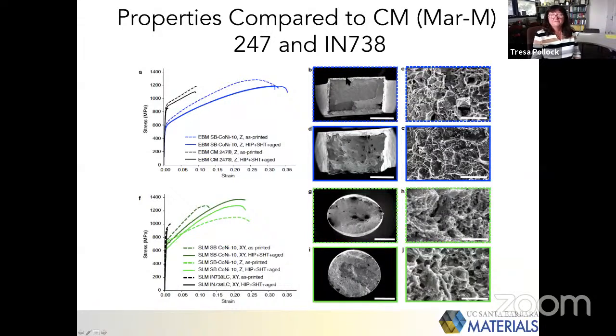And so recall the alloy I showed you earlier, Mar-M 247. This is the one that prints, that cracks very badly as one prints it. And so I'm showing the properties of the nickel cobalt alloy that I just discussed in comparison to that Mar-M 247 alloy and another similar alloy, IN 738. So these are both nickel-based alloys with high volume fractions of precipitates.